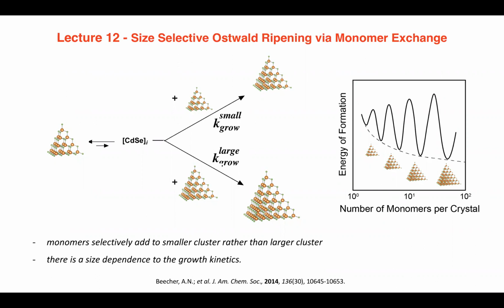I think it's not a single rate, but a collection of many rates that are all working together. That gives, we think, this very unusual property where things tend to pile up, and to get to larger sizes you have to heat up. Going from one pyramid to the next, we had to heat it up. So the take-home message here is that this stuff is down in the weeds in a way. It's detailed and complicated to work through. I hope you'll take home more, but your reflex should be that it's hard to grow crystals.